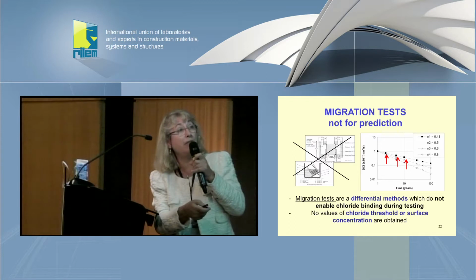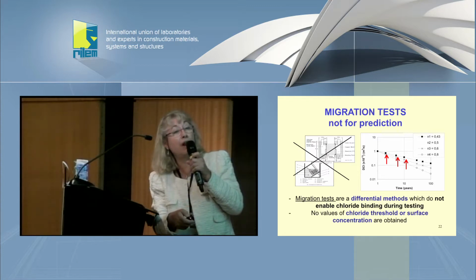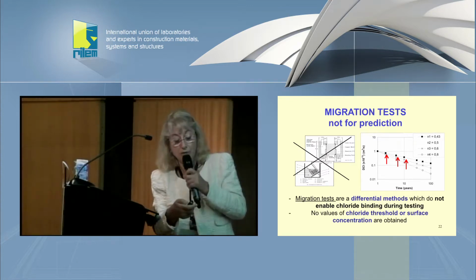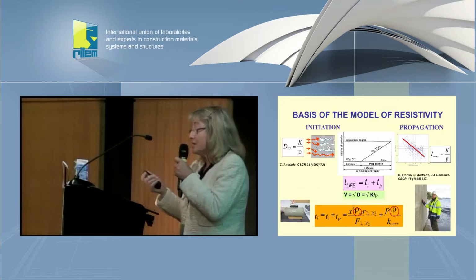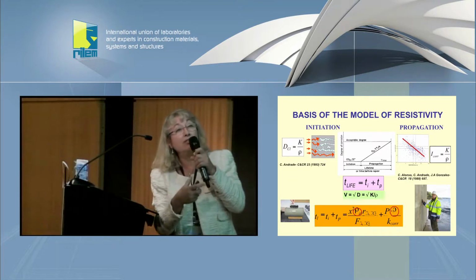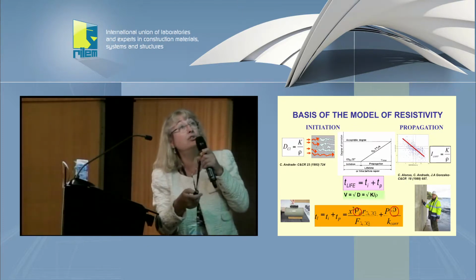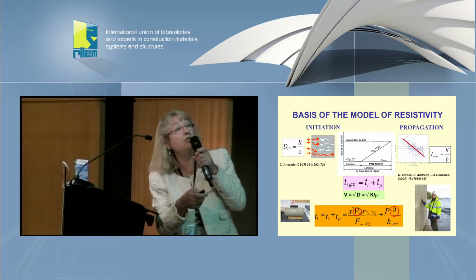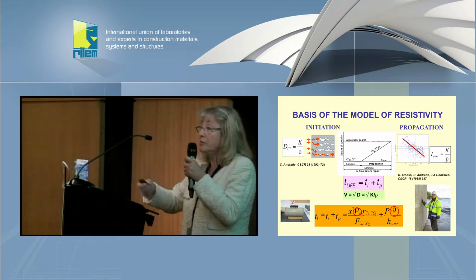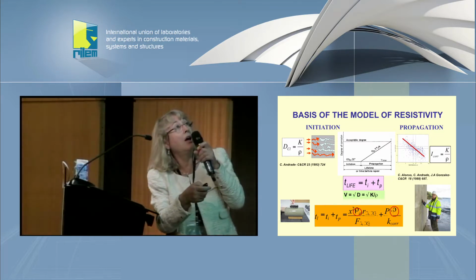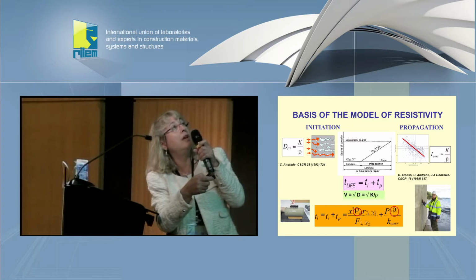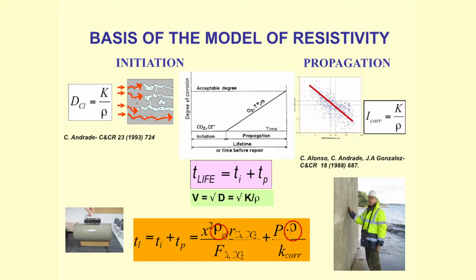This is a differential method that does not enable chloride binding during the short time of the testing, and no values of chloride threshold or surface concentration are obtained. I am in favor, as several of you know, of resistivity, because if you really like a very rapid method, resistivity is non-destructive and able to give the same information as the other methods. Moreover, you can leave the concrete inside the salt solution and follow the resistivity after several times in contact with salt solution. We have developed a model for the initiation period based on resistivity and its relation with the diffusivity, and also with the corrosion rate.